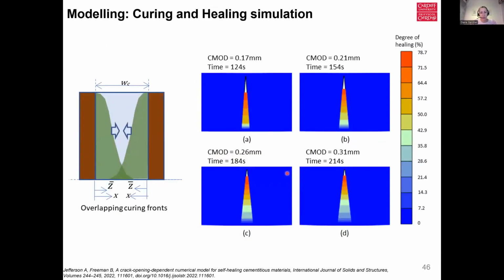So looking at how that depends on the crack opening and the rate at which that crack opens, and look at how that curing front progresses and the viscosity change with curing. And that allows us to understand how that material builds up in the crack, how it cures, how it heals, and therefore how that healing component can be reflected in the finite element model.